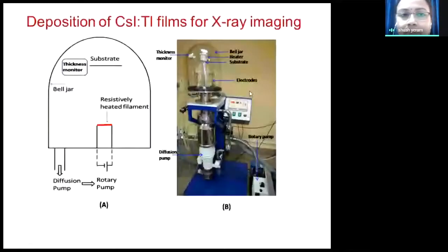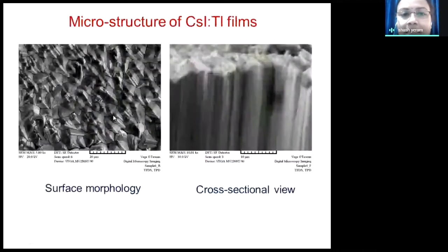So how can we use that? First, one is cesium iodide thin films, which we are working on. Any material scientist or PhD student who is working on thin films will know this is a thermal evaporation system. Very easy to use and very economical, and most labs have this. We put our cesium iodide on this resistively heated filament, and put our substrate, which is generally quartz plates, on this, and evaporate the cesium iodide, and we get this kind of films.